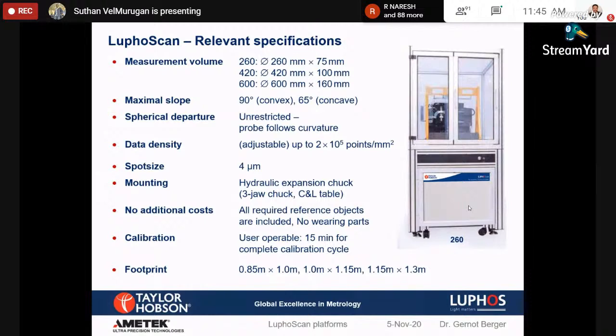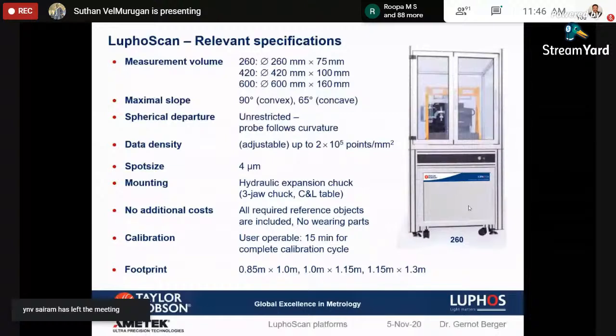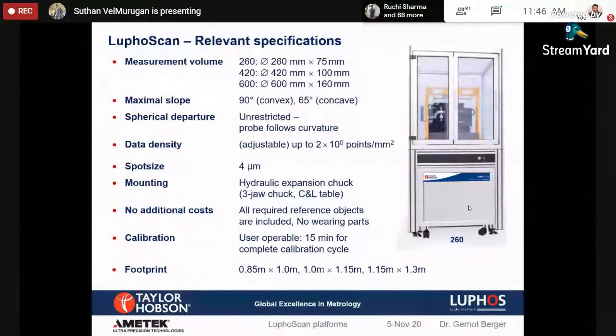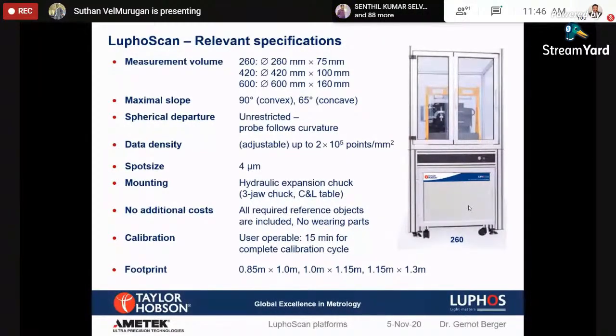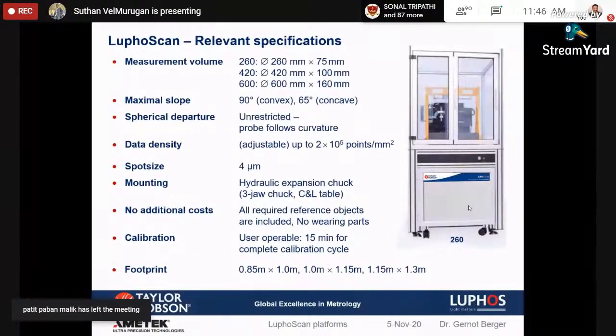It's only one line. So if you are trying to cover the entire 3D surface, it is going to take more time, probably 15-20 minutes. But in the non-contact, there is nothing going to touch, so we have no limitation of the speed. Unless we get very good data from the machine, we are able to rotate at any speed. If it rotates at 100 RPM, for a 100 millimeter diameter part, probably we can measure the entire surface finish within 2 to 3 minutes. That is the major difference and major advantage of the non-contact against the contact profiler.